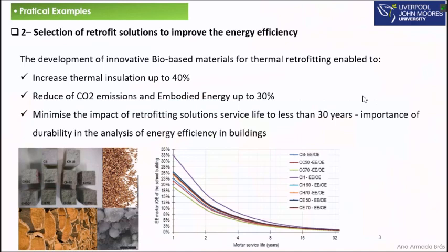So the development of innovative bio-based materials for thermal retrofitting enabled to increase thermal insulation up to 40%. What did we test? We did some laboratory tests using different bio-based materials, namely a very famous one in Europe, which is cork. I know that we don't have cork here, I think. 50% of the cork is exported from Portugal, and it comes from the trees. Then we incorporated the cork granulates into new mortar compositions, and we compared with traditional solutions.